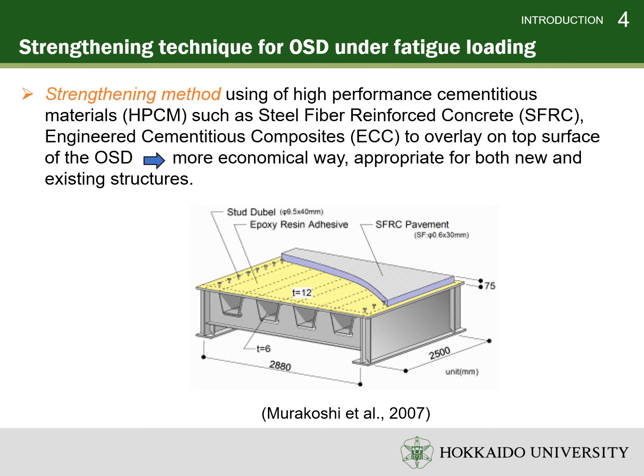One promising technique that is appropriate for both new and existing bridges is to overlay high-performance cementitious materials such as steel fiber reinforced concrete (SFRC), engineered cementitious composite (ECC), and ultra-high-performance concrete (UHPC) on the top surface of the steel bridge deck to improve the fatigue-resistant capability of the structure. It has been found that the stiffness of the bridge deck has been enhanced via significant reductions in stress level and range at the critical locations in the steel members.